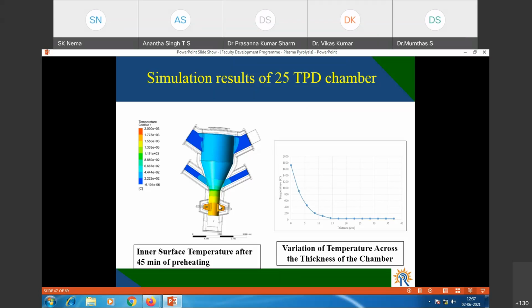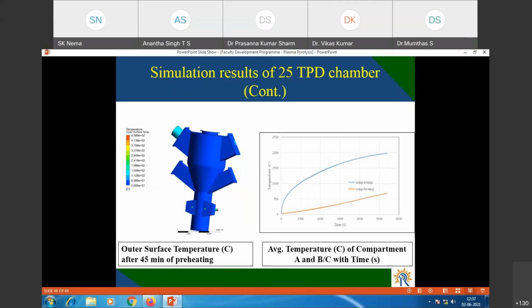The temperature profile should be properly maintained, so that you do not form toxic things, and you can convert waste into useful gases rapidly. So this will work in the gasification mode, and you are going to convert this waste into useful gases. Again, this temperature profile is telling you the outside temperature is going to be lower. So when the system is going to run, the outside metal temperature should be room temperature or slightly above room temperature. It should be less than 50 to 60 degrees centigrade.